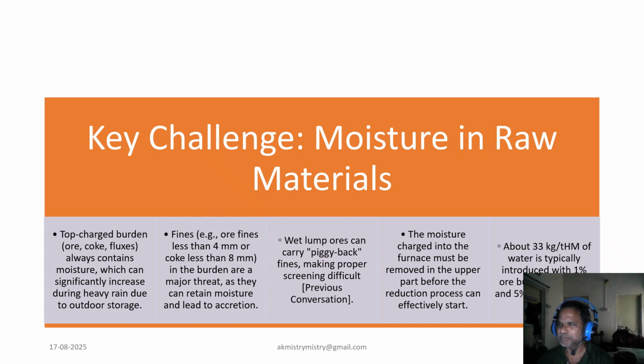To put this in perspective, approximately 33 kg of water per ton of hot metal is typically introduced with just 1% ore burden moisture and 5% coke moisture.